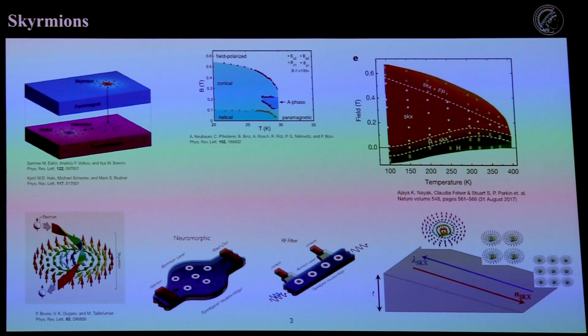What's nice about this is that from 2009, within 10 years, we went from below 30 Kelvin to up to 300 Kelvin for stabilizing Skyrmions. This is very nice for the field of condensed matter physics because, as you know, superconductivity has existed at a very low temperature for a very long time. What's also nice is you can stabilize Skyrmions in zero magnetic field. This is the phase diagram for one of these Heusler compounds, which stabilizes this anti-Skyrmion. I will explain very quickly what that is in a moment.